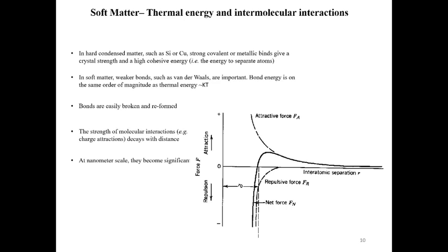For metal material, usually you have to heat up the material to their melting temperature, which often is 1,000 degrees. That is a pretty large amount of energy you have to provide to the system in order to break the bond. However, for the softer material, the energy you provide is sometimes just a few kT, which means the system can be reorganized even at room temperature.